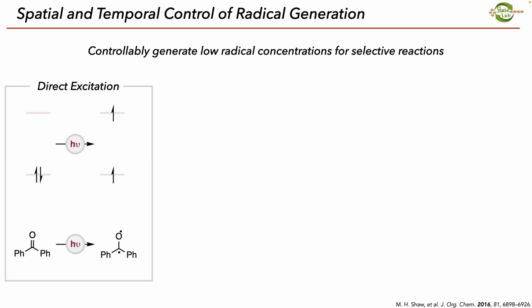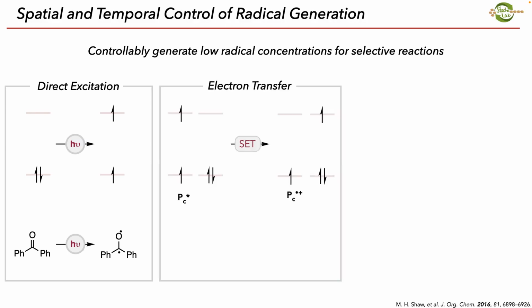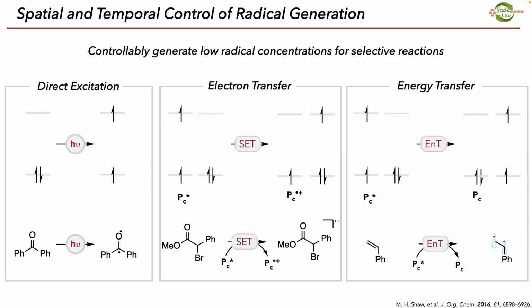So we can do this a few different ways. We can do direct excitation, where the molecule itself will absorb light and move into an excited state and do chemistry. We can do this with a photocatalyst, which can absorb the light and then transfer that energy to a molecule, like a single electron transfer process. Or it can undergo energy transfer, where it transfers that excited state energy to the small molecule and then generates an excited state species, which can go on and do chemistry. In all of these cases, we can do this very controllably by controlling the concentration of the photocatalyst or the substrate and the wavelength of visible light.